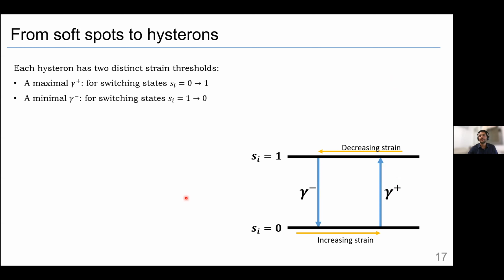Now we want to make it even simpler. So we take the soft spot and make it a hysteron. So hysterons are the basic static element. Each hysteron has a gamma plus and a gamma minus value. So it has two states, 0 and 1. It starts, for example, in the 0 state. You increase the strain. When you reach gamma plus, it switches states, gets to S equals 1. And then you decrease the strain, it gets to gamma minus and switches to 0. So this is the basic hysteresis loop.